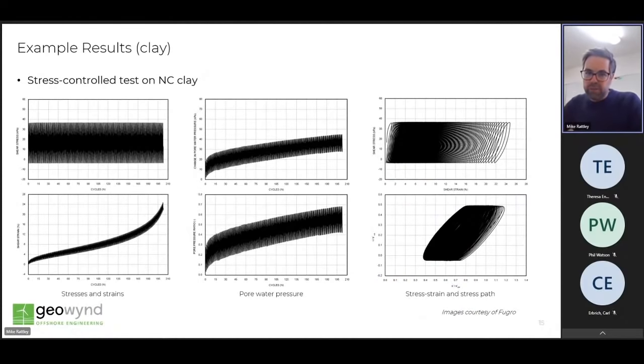So although I'm a bit pressed for time, I just wanted to include a few examples of results to illustrate good quality cyclic tests, mainly for later reference. Shown on this slide are results from a stress-controlled cyclic DSS test on a normally consolidated clay. And you can see gradual accumulation of shear strains and excess pore water pressures increasing with number of cycles. That's evident, along with the gradual reduction in cyclic stiffness, which is consistent with the material type.